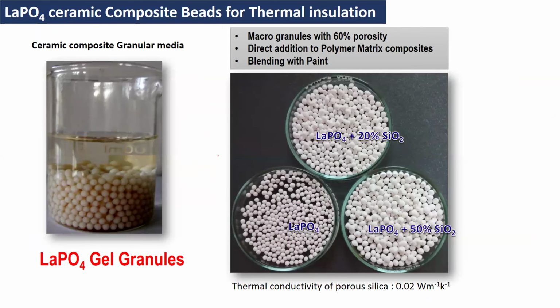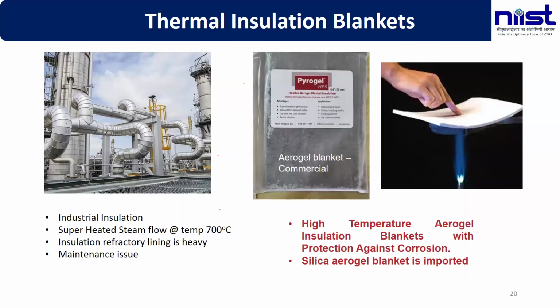And apart from that, we also worked on granules. Granules means silica, lanthanum phosphate, aluminum oxide granules, which are refractory granules, and this refractory granule is extremely important for thermal lagging. This lanthanum phosphate and silica granule, whatever we have made, we have tested its thermal conductivity, and also we have embedded this lanthanum phosphate silica in an epoxy matrix, and finally we could make a super thermal insulation composite material.